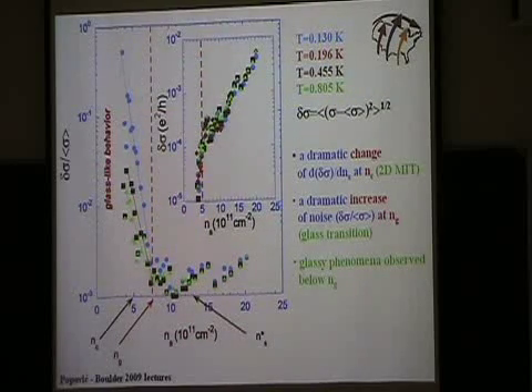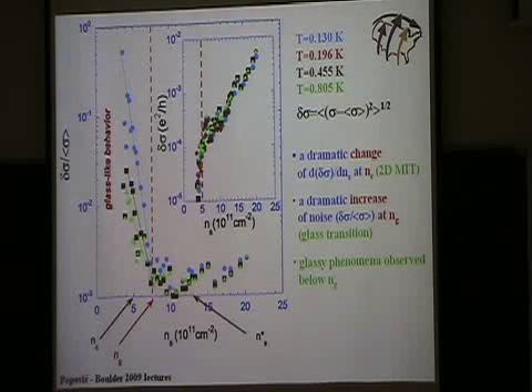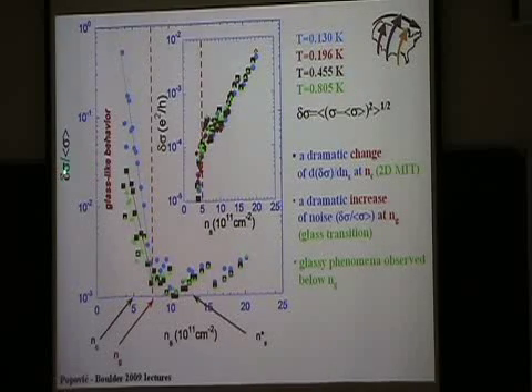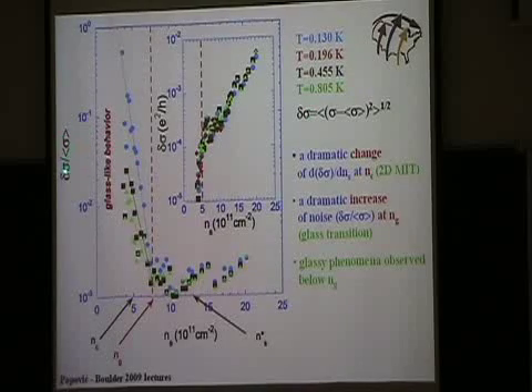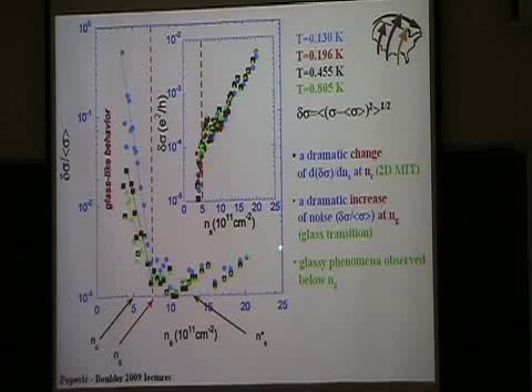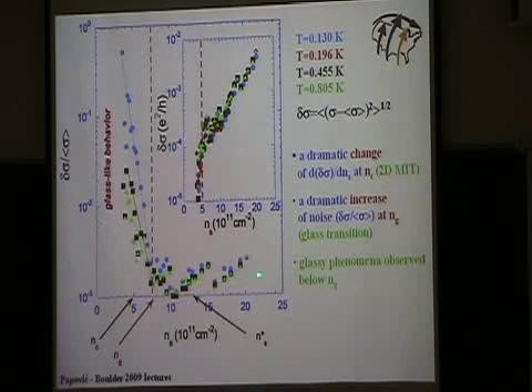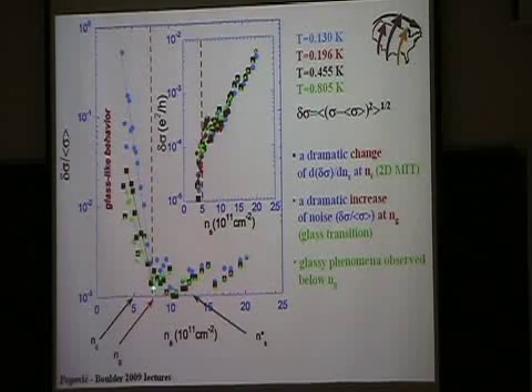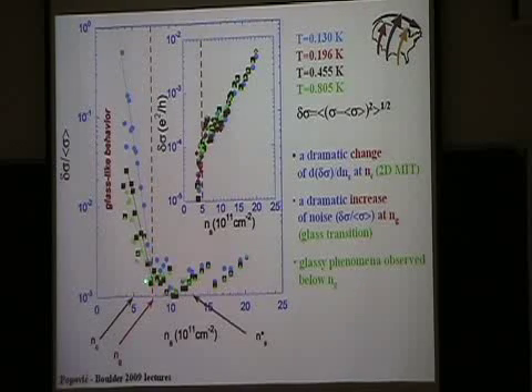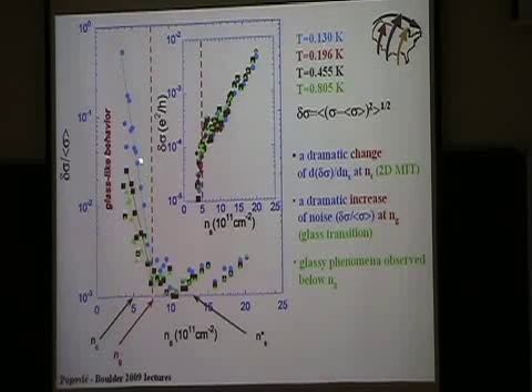I'm showing it because it still shows dramatic behavior. So this is the noise, standard deviation divided by the average value over a fixed time interval. And you can see that at high densities, within the error of the measurements, there is no density dependence. And then at some density, the noise starts to increase exponentially. And this increase is steeper for lower temperatures.